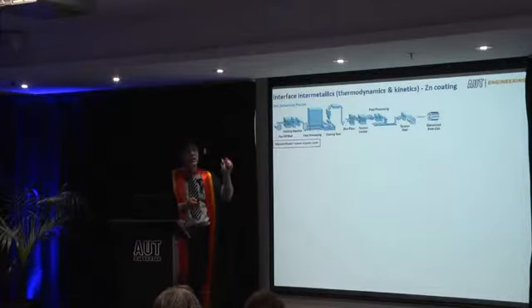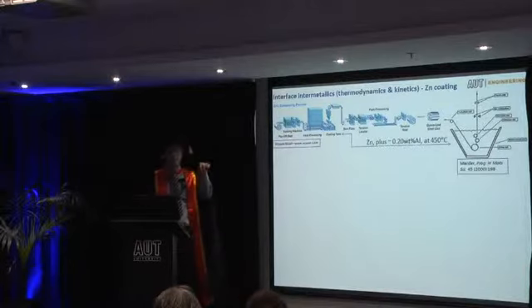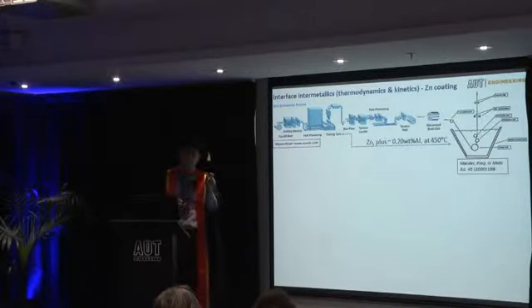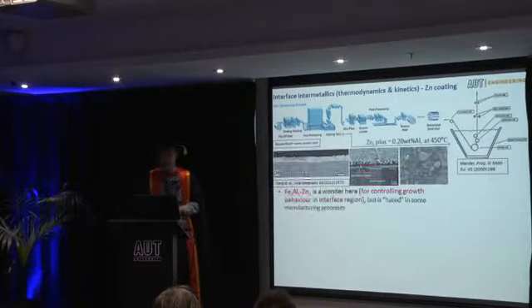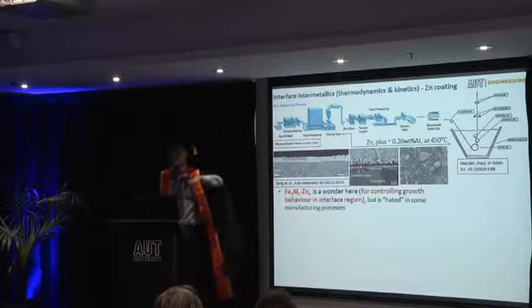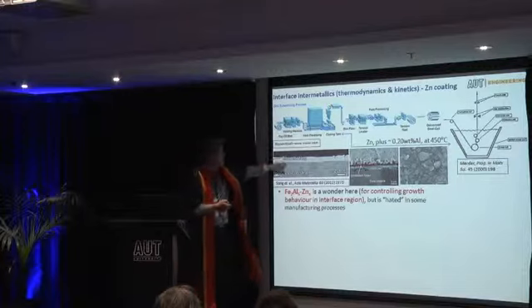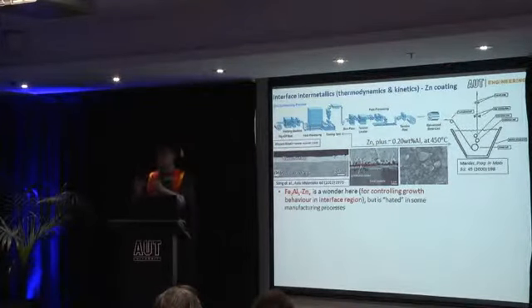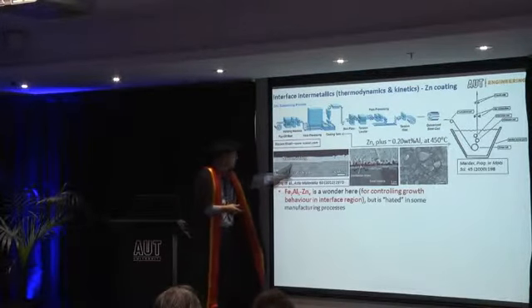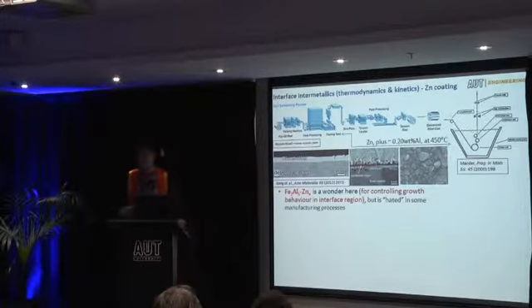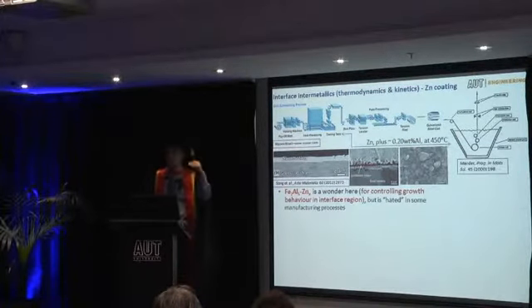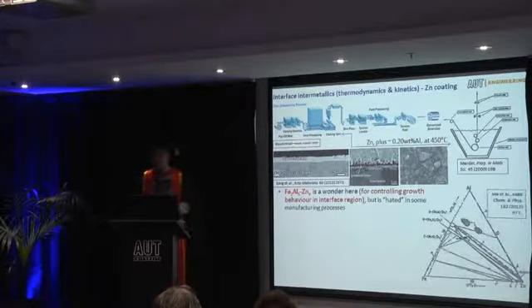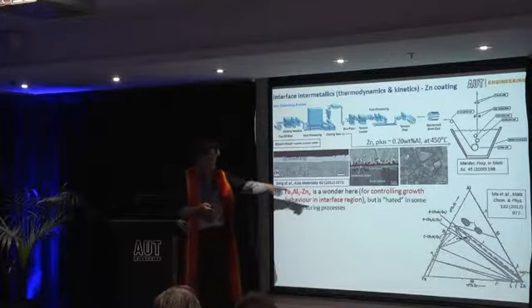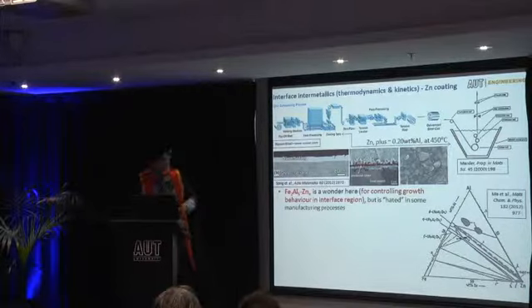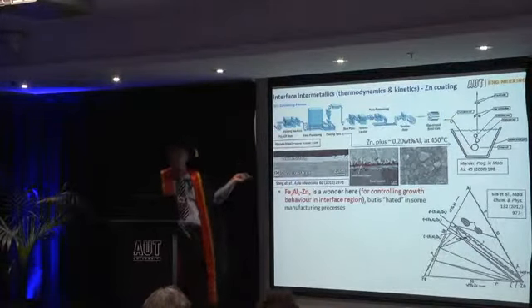This is even more so if you look at the so-called continuous galvanizing line. This is a process where all those galvanized sheets go through those procedures very, very fast. If you look at the zinc bath, the zinc is alloyed with about 0.2% aluminium. It turns out that with that 0.2% aluminium, during that short dipping time, you don't have intermetallic growth. So you end up with a very even coating, about 20 microns of zinc, which is reasonably deformable. So this turns out to be a very good compound in between, because it inhibits the normal growth. I put up this one here where the author, Marder, used that diagram to explain the mechanism, why that worked.